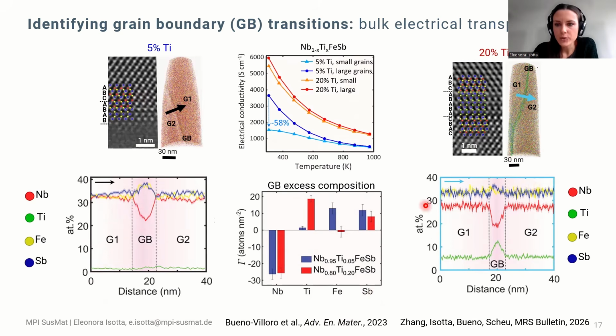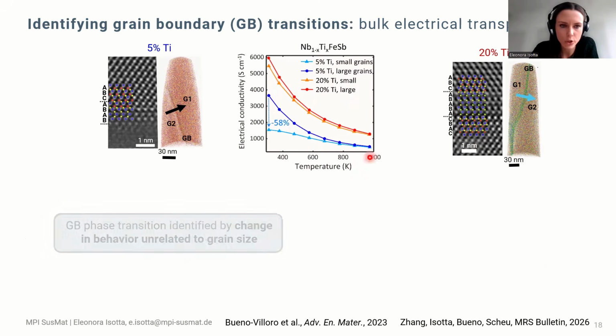And in the case of 20% titanium, the grain boundary happens to be also poor in niobium, but this time rich in titanium and antimony. So there was really a change in the chemical composition of the grain boundary, a grain boundary transition, that was responsible for the change in properties that were observed.